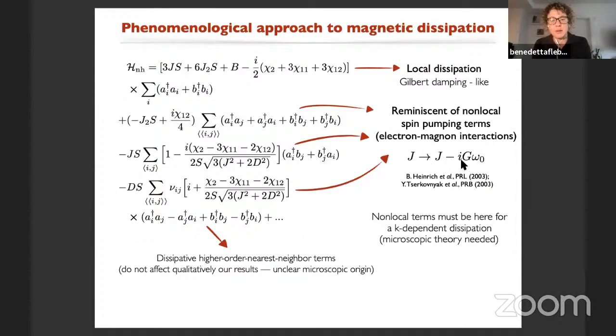So here you have J, and you know that you also have a dissipative contribution due, in this case, to the phasing between magnon and electron spin. In our case, these come out from trying to fit the ab initio results of dissipation due to magnon-phonons. So again, to our knowledge, there is not really a microscopic theory available, but it would be definitely very interesting to look into it. And then we also have some higher order, nearest neighbor, purely dissipative terms that microscopically make less sense to us, because we tend to think that if we have a dissipative interaction, we will also have its non-dissipative counterpart. However, retaining or not these higher order terms does not affect our results.